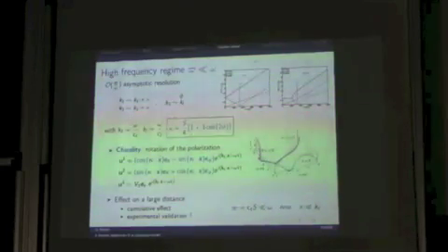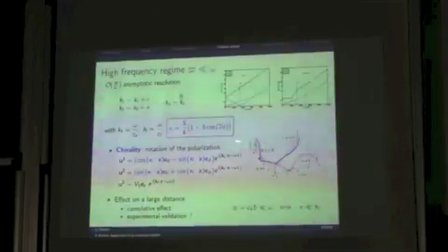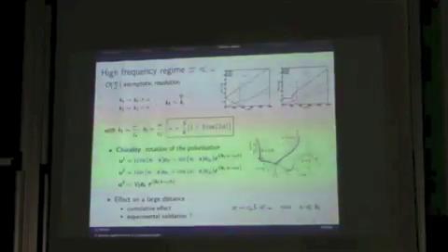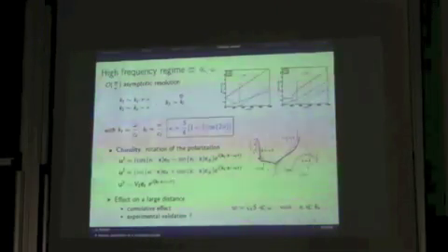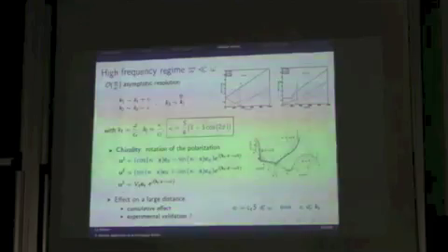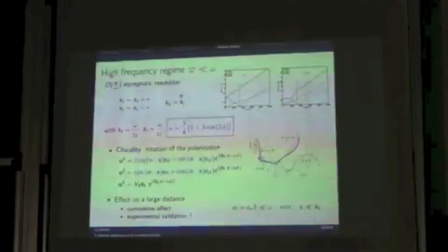This shift, kappa, is related to the angle. It's not the same when you change the direction of the plane wave according to the direction of the Burger vector. And in fact, if you check the polarization, you observe a chirality related to this shift. This chirality means that when you are in a medium with defect, what you observe is a wave which has a typical wave number, very high frequency regime, so with a millimetric or maybe less wavelength.